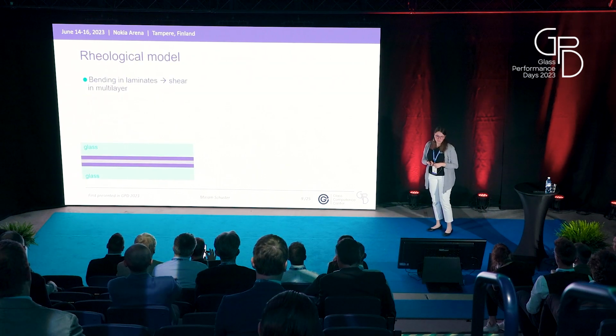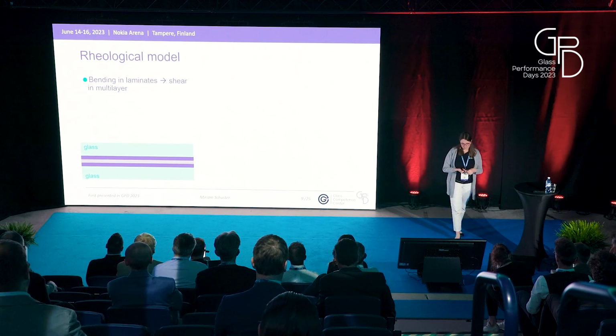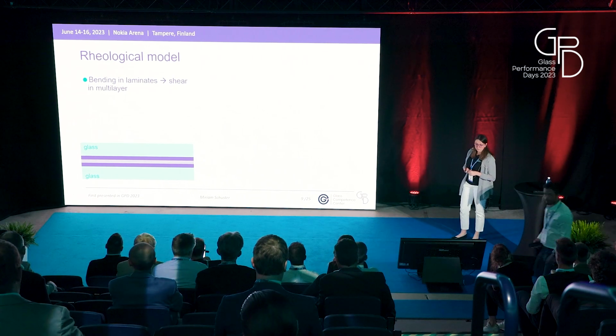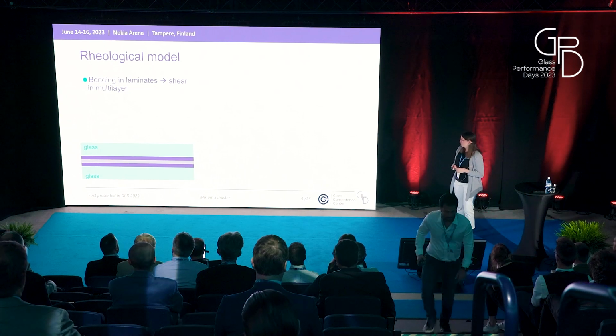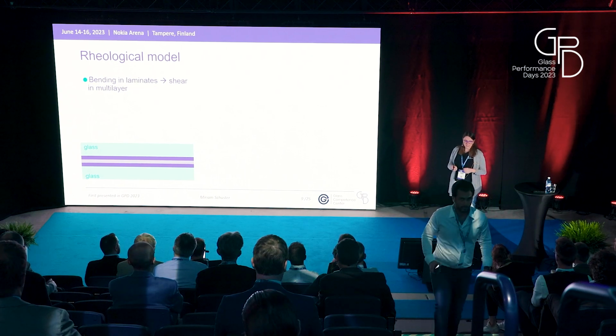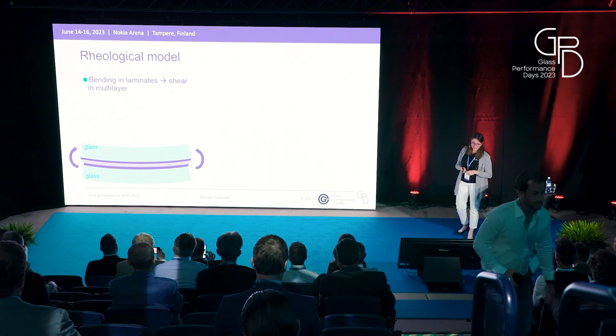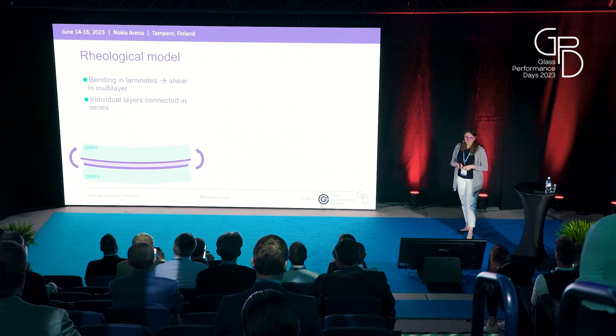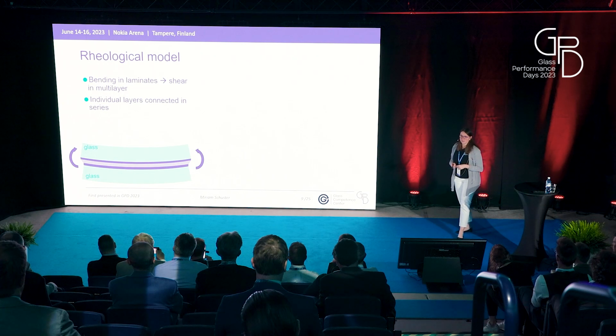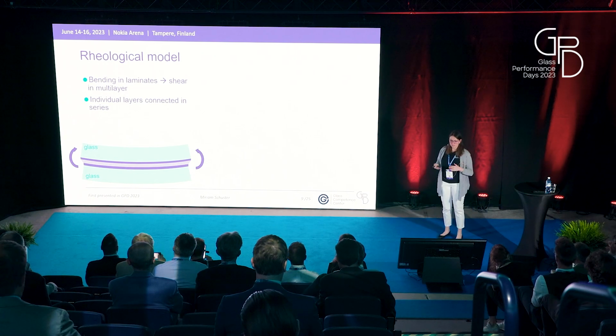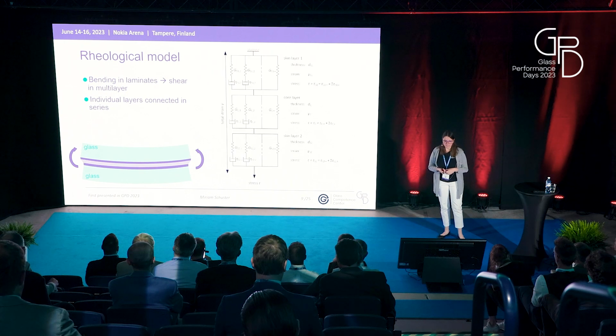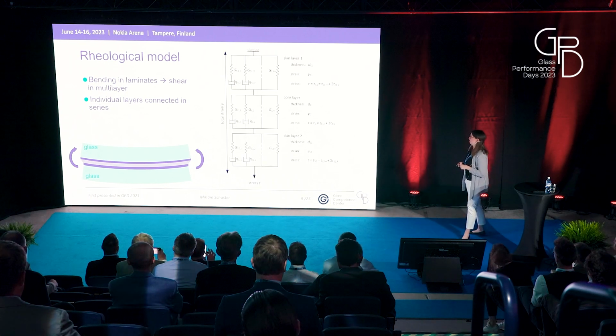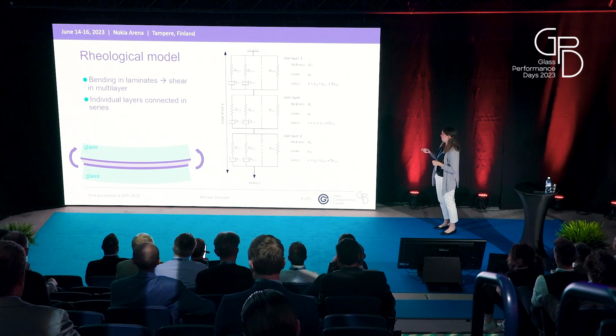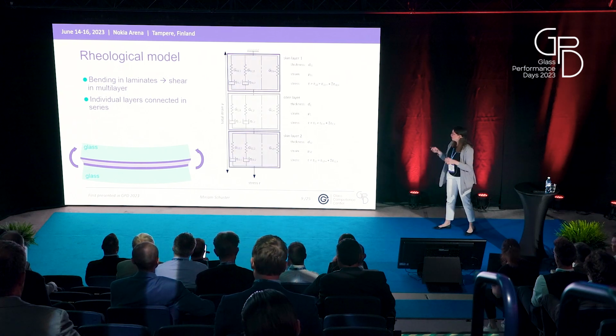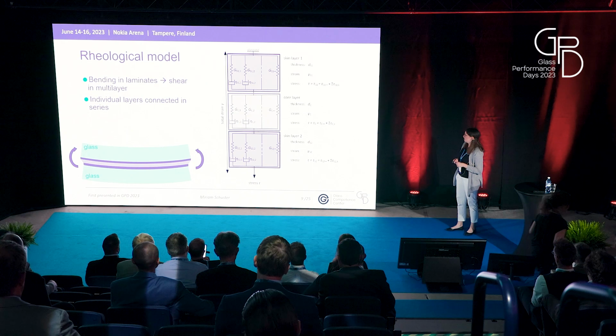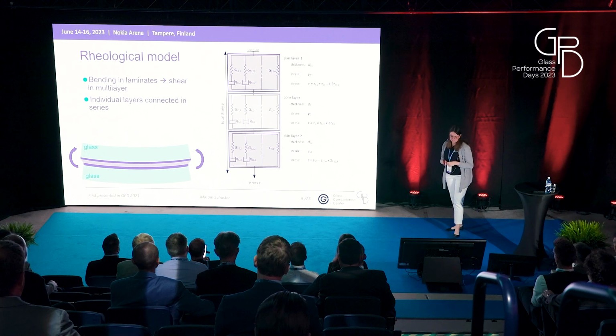Okay, now let's have a look at multilayer interlayers. So we have here a glass with a multilayer. In this case, it's a three-layer. And when we bend this laminate, then we have shear in our multilayer. And we see that the individual layers are connected in series. So when we want to transfer this to rheological models, then we have the three generalized Maxwell models for the three layers connected in series. With the dark color, we see the skin layers, and the lighter color in the middle is the core layer.